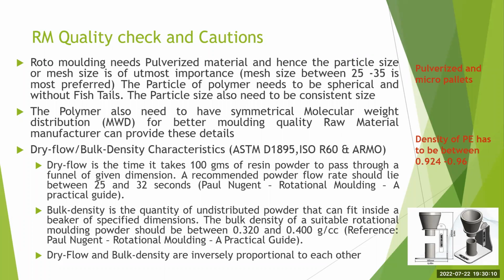When you are saying 25 mesh, it should be plus or minus one mesh. When you say 35, it should be 34 or 36, not beyond that. If it is 35 mesh powder and you have 25 mesh in it, and you have got 38 mesh in it, it is again a problem, because the lower the mesh, it will melt less, but the higher the mesh you go, it will melt fast, and there will be differential temperature which can decompose the polymer or oxidize the polymer. So you have to be very, very cautious about it.